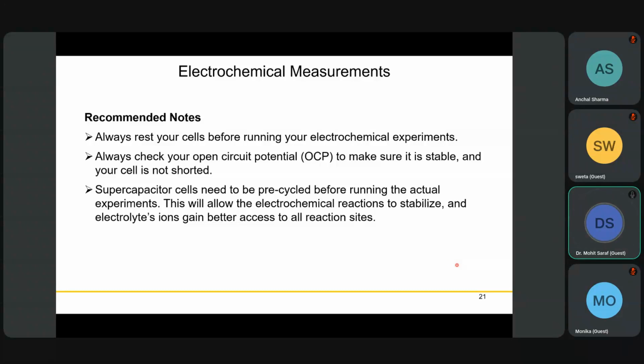We always need to check the open circuit potential (OCP). If this OCP is changing, the first impression is that there's a problem in your system, maybe it's not stable, or the connection in that particular channel is not stable. So if you check the OCP as soon as you assemble your cell on the electrochemical workstation, it gives you an initial impression of whether your cell is stable or not.